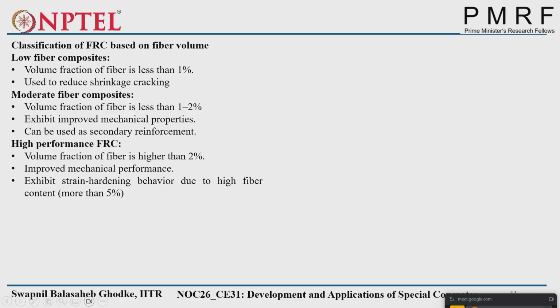So, I am discussing the classification. What do we call low fibers? If the fiber content is less than 1% of the total concrete matrix, that is called low fiber composites, and that is mainly used to reduce shrinkage cracking. If the fiber volume is between 1 to 2%, that is called moderate fiber composites, and it exhibits improved mechanical properties and can be used as a secondary reinforcement. Means already you have the rebar reinforcement, and these fibers are called a secondary reinforcement.